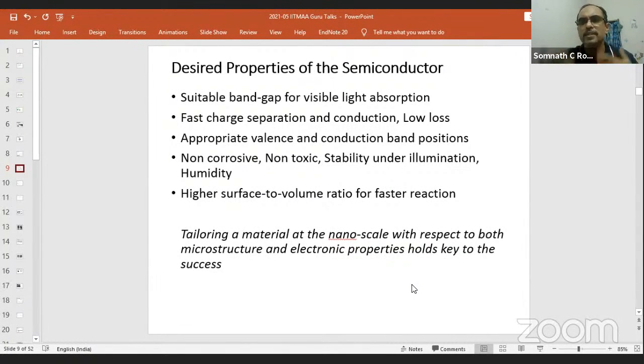We are not too interested in the entire IR, because IR has its own heating effect, which can degrade the material. Of course, there are materials which can efficiently absorb IR, but even if you can absorb 40 to 50% of the entire solar spectra, that is from the UV to visible, that's good enough. Then the second is fast charge separation and conduction, low loss.